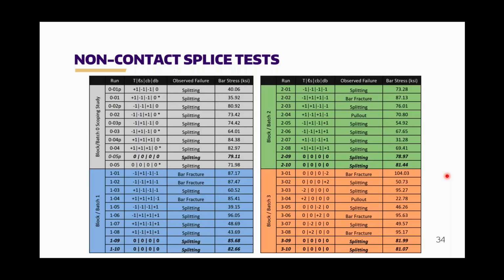Here's a little bit of a busy slide, but it breaks down each specimen that we cast and tested. So overall, we tested 40 specimens. Batch 0, that gray block, is the investigation of the use of primer. And then the blue, green, and orange are batches 1, 2, and 3, which were the main component of this test. Not to go too much into it, but you can see those pluses and minuses are how far from the center point we went for each point, as well as the observed failure and bar stress, and Travis will go into that in a little bit.